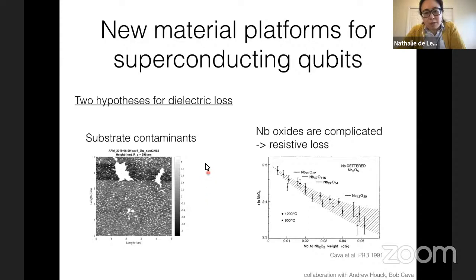So our two main hypotheses were, one, that you can have a lot of contaminants on the substrate and on your device that just lead to dielectric loss. To give you a sense of the scale here, if you have a loss tangent of something like 10 to the minus 3, which is a pretty typical loss tangent of stuff in general, and you put that on top of a qubit that has a surface participation ratio of something like 10 to the minus 4, which is a pretty standard number, then that limits you to a Q of around 10 million, which is very close to the limits that people see right now. So this 100 microseconds is a Q of around 1 million. It doesn't take very much to give you exactly the losses that people see.